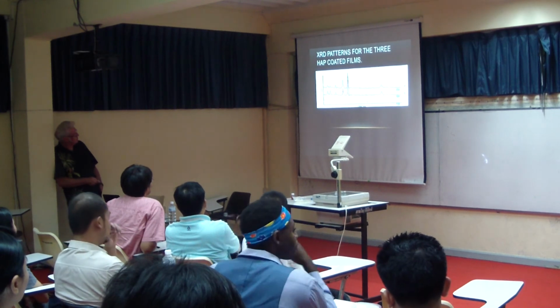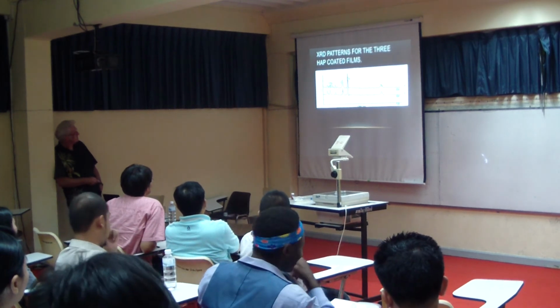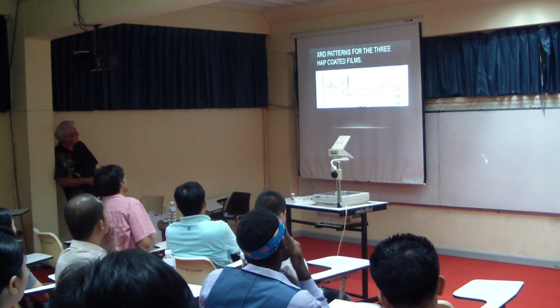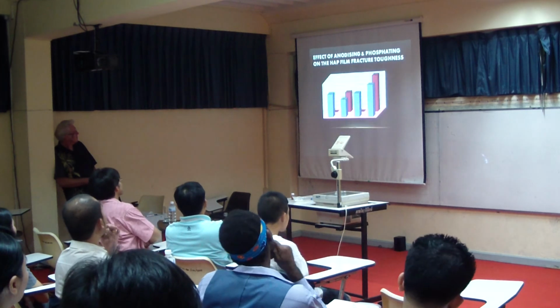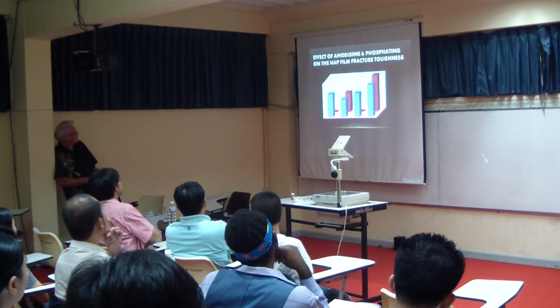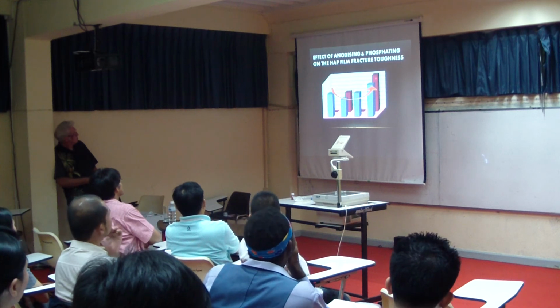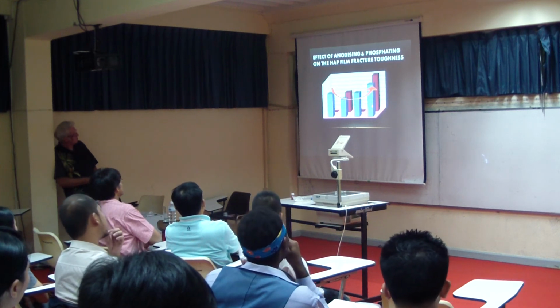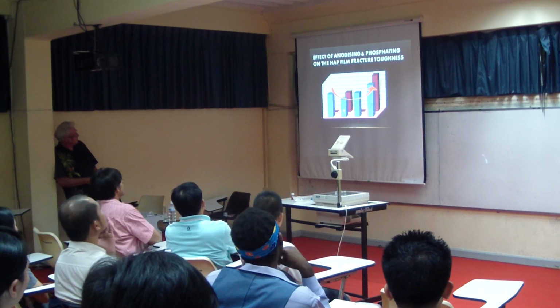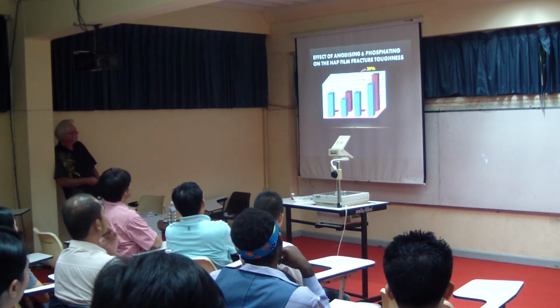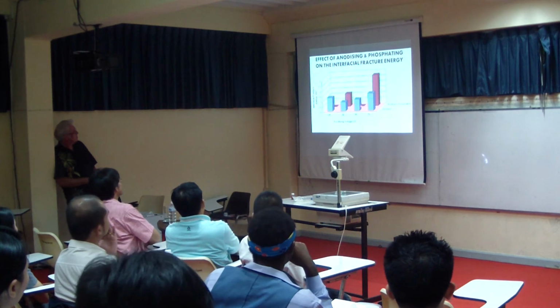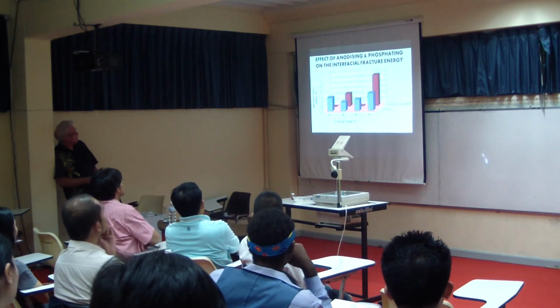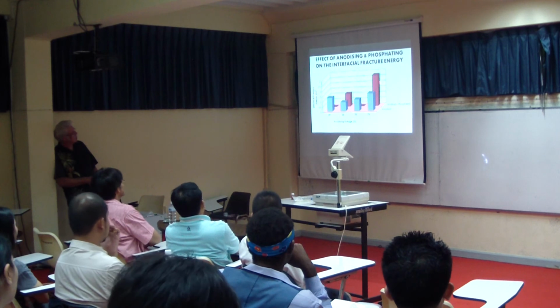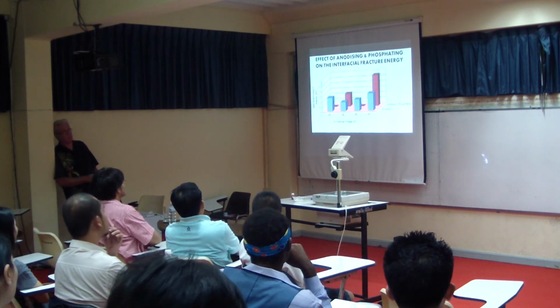We did some X-ray diffraction and we showed that there wasn't a big change in phases. This is the hydroxyapatite peaks, this is the titanium peaks. And we saw that we got some increases depending on, this is 75 volts, this is 50, and this is 25 volts. And we could measure the interfacial fracture energy. So we showed that, yeah, we can control the properties, and the properties were pretty good.